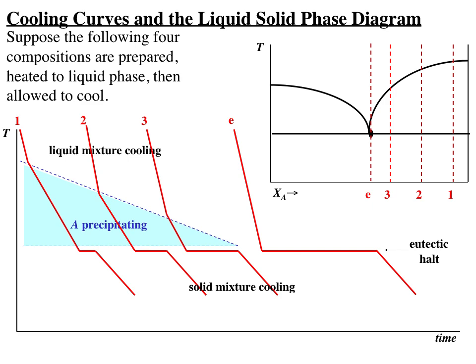Again, when I look at the cooling curve, temperature falls nice and linearly with time, but then there's a first discontinuity. And at the first discontinuity, the pure A will begin to come out of solution first. Why? Because I'm to the right, coming down along isopleth 3. As I make the tie line connecting, I come to the phase boundary where liquid begins to occur. And I make the tie line, it hits the liquid, the liquid one-component mixture and the pure A axis. So A begins to precipitate out. And again, there's a nice diagonal for that. And as the A begins to precipitate out, the solution gets richer and richer in B.